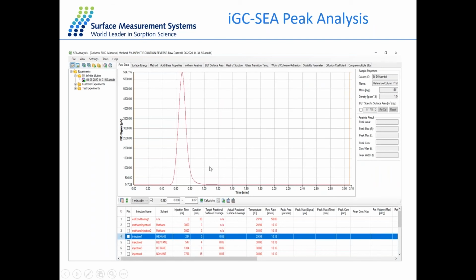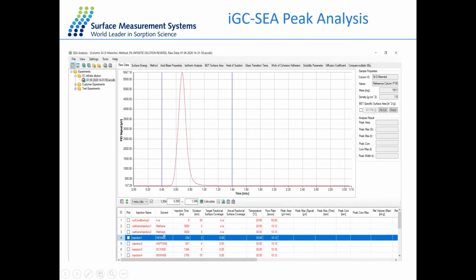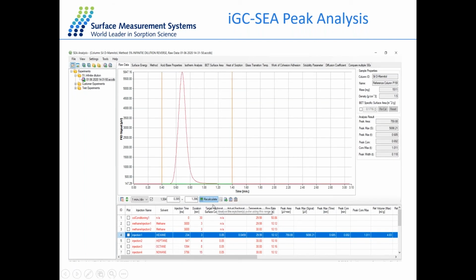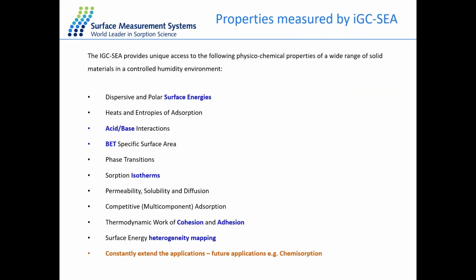So peak analysis is relatively quite straightforward. In this example here, we've injected a few non-polar molecules. We've also injected some methane. So this is to calculate the dead volume. This is as a result of one of our hexane peaks. What you do is simply select the beginning and the end of the peak and click calculate. And in this case, as you can see, all these parameters here will start filling up. So analysis is automatic. However, if you did want to export some raw data and do some back calculations, that's also a possibility too.